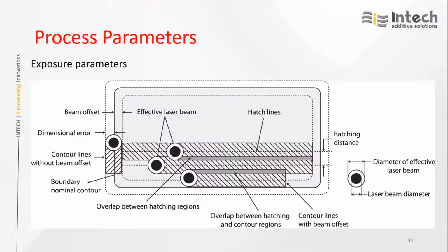If this is not happening, in the vertical section we'll get porosity. Within the layer, if the hatch distance is not proper, here also we can see lack of fusion. So these four are the key process parameters which we need to optimize to get a good quality, good density component.